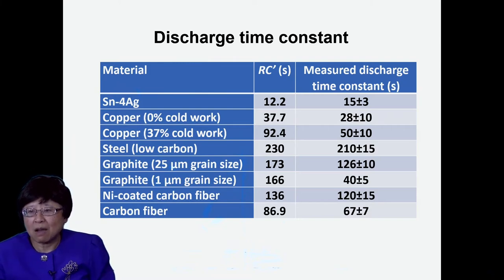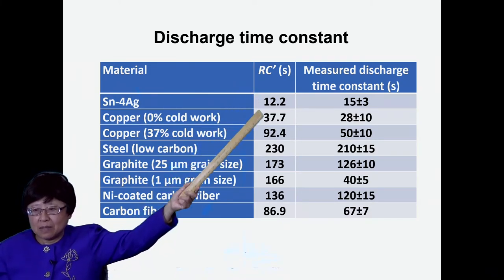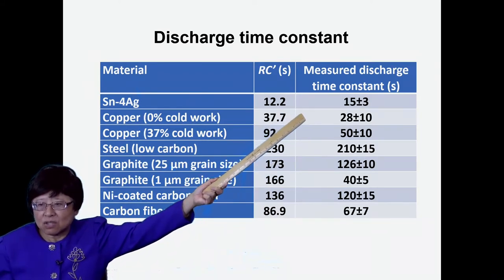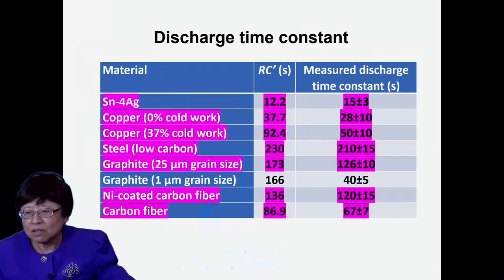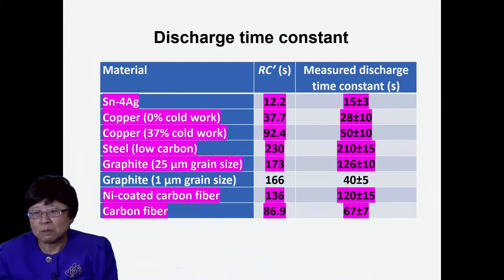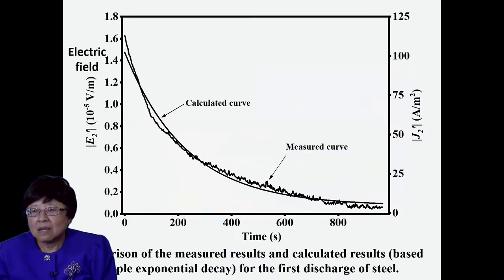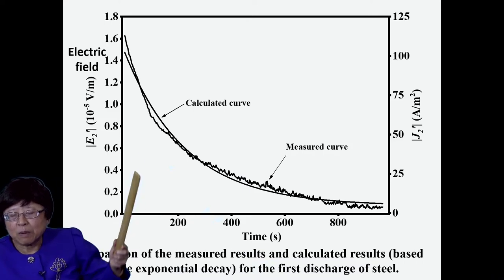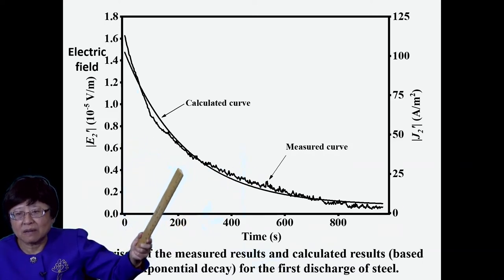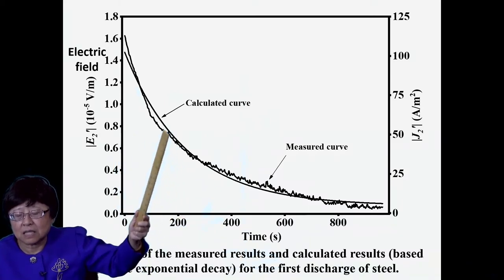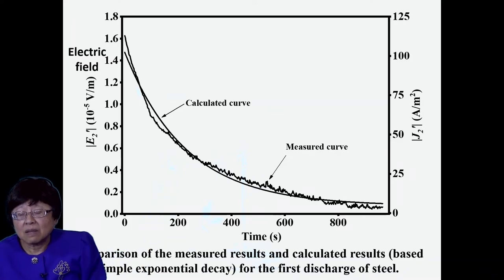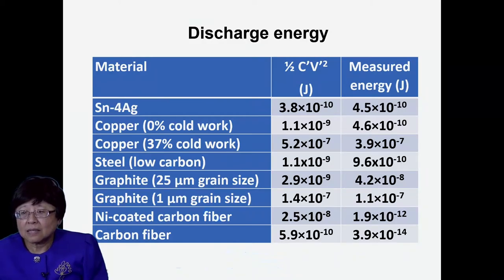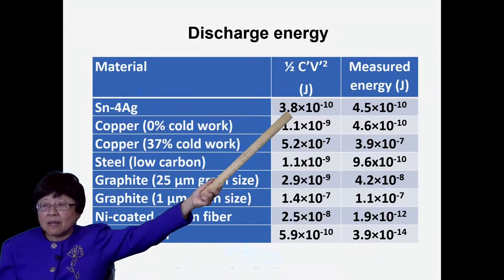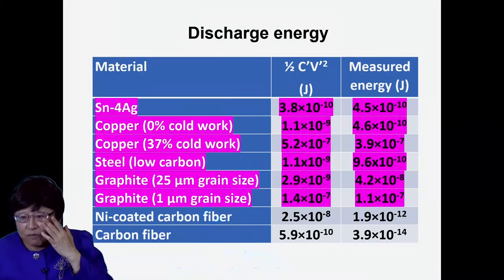The discharge time constant, calculated as RC prime, is shown here for various metals and carbons, and the measured discharge time constant is shown here. The two pretty much jibe for the vast majority of these materials. And the exponential decrease is shown here. The discharge curve is simply fitted with an exponential curve, supporting this RC time constant idea. The discharge energy is calculated as half C prime V prime squared, and it's also measured, and the two agree for most of the materials.